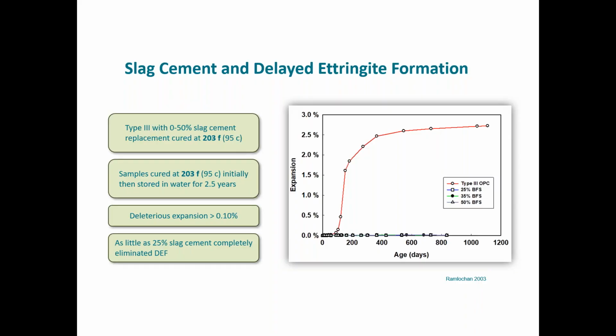Now, this is a chart that the first time I saw it was mind blowing to me. We talked about delayed ettringite formation and how critical an issue it can be, albeit rare. When it happens, it's destructive. This was done at the University of Toronto, where they used Type 3 cement. Type 3 cement is known for being finely ground. A lot of times it can have high C3A. I don't know about this particular cement.